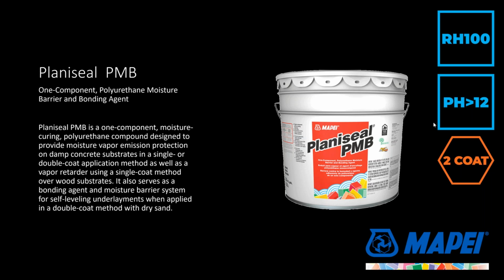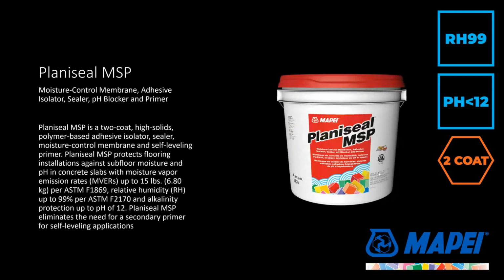But again, 2 components, 2 applications of PMB with sand broadcast for leveling applications, 2 coats directly for loose lay applications on the top. We're recommending that as well. 1 coat of Planaseal PMB works if you're using our urethane or MS wood adhesives for the wood installation business. We'll talk a little bit about that when we get to wood stuff. But this, in my opinion, is one of the silver bullets for wood floor claims. A simple coat of this on a porous concrete or even plywood deck will, in conjunction with any of our urethane or modified silane adhesives, create a great base for wood floor, protecting it from damage that might be caused from subfloor moisture emissions.